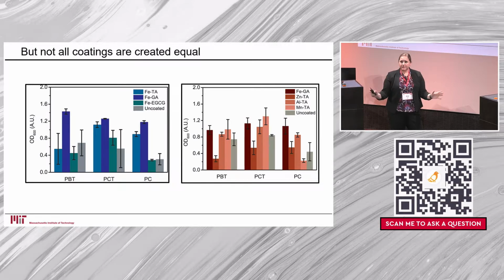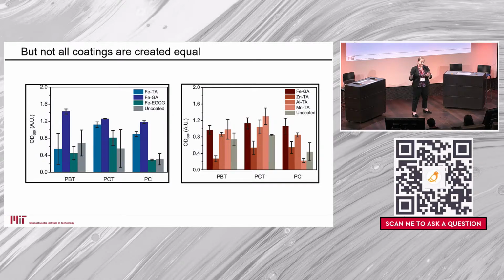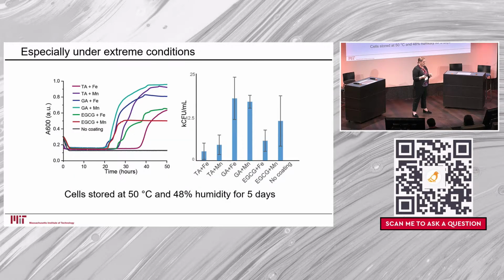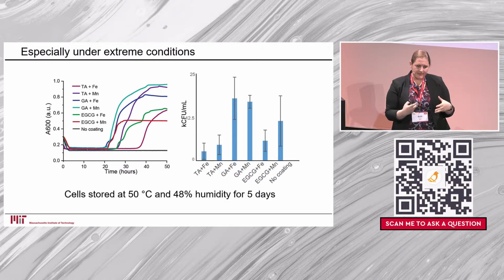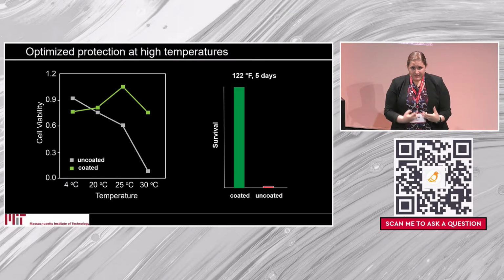Importantly, I showed you a bunch of different components we could use for these coatings. So what these two graphs are is just different combinations of those polyphenols and metal ions. And what I want you to take away from this is that not all the coatings work effectively for every stressor. So that's where the optimization here comes in. We can see this when we heat cells. So these are P. chlororaphis, those nitrogen fixers. And we can see that based on the polyphenol we use and the metal ion, we get very different viability of cells, and that just means the number of cells grown. So on the left, that's the peak of that curve, and on the right, that's the tall part of the bar graph. But when we optimize this, we get really incredible results.